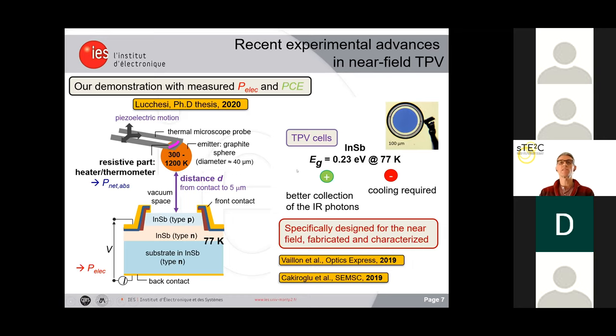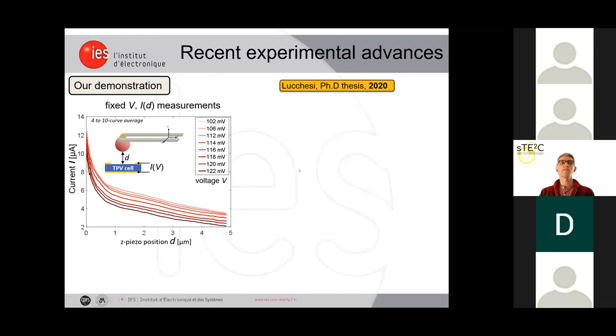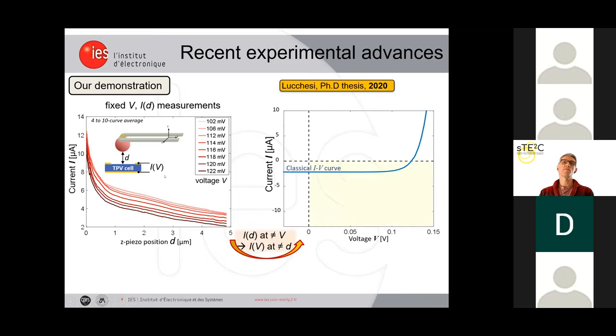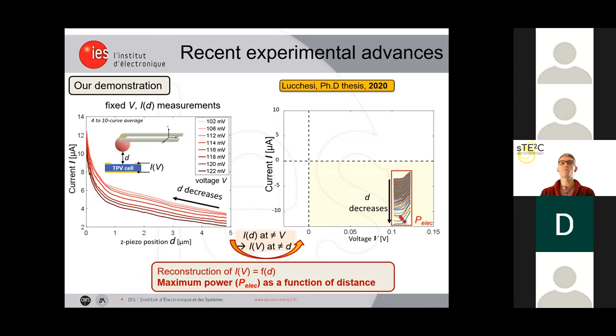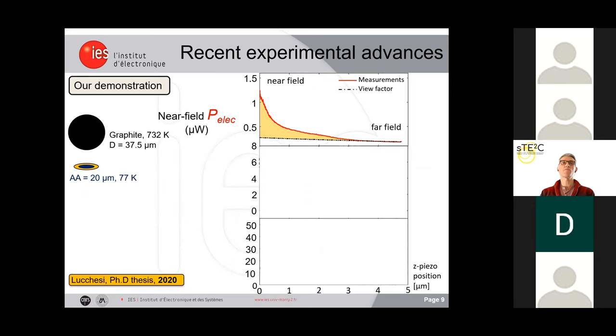So the cells were specifically designed for the near field, fabricated and characterized. But the way the measurements are done is this. So the current is measured as a function of distance for different voltages. Then the usual IV characteristics can be reconstructed, and we see the evolution of these IV characteristics as the distance between the emitter and the TPV cell decreases. Then it is possible to determine the electrical power at the maximum power point as a function of distance. So this is what we have done here.